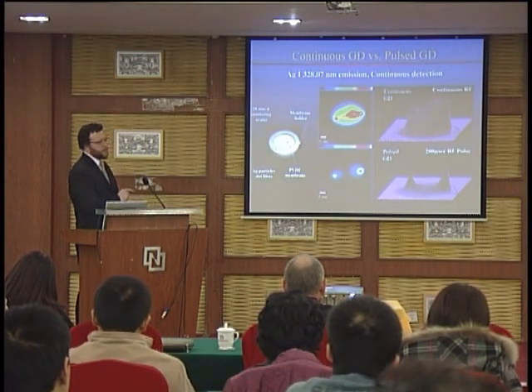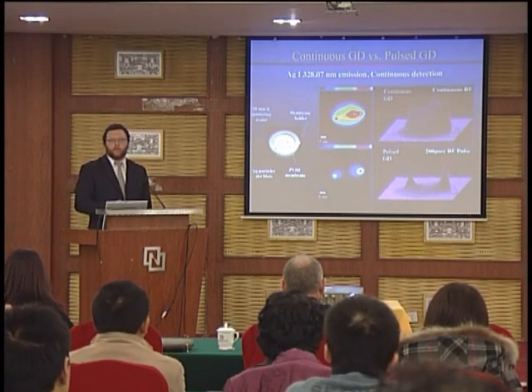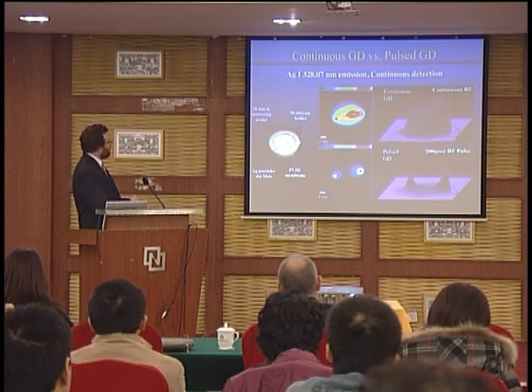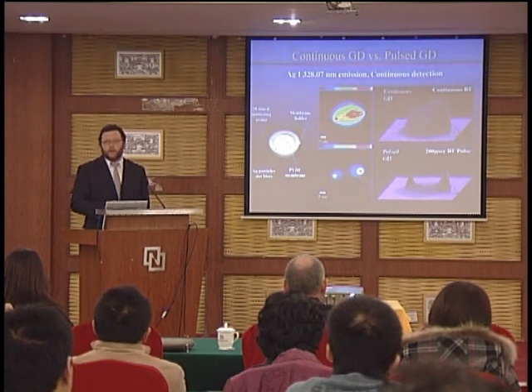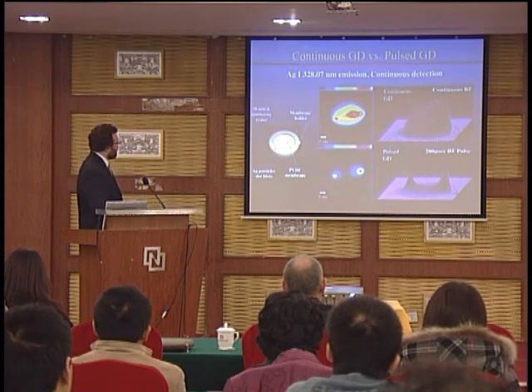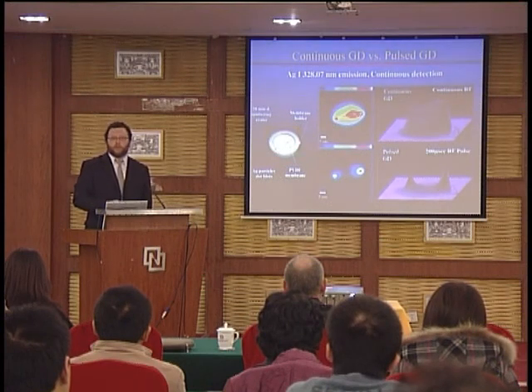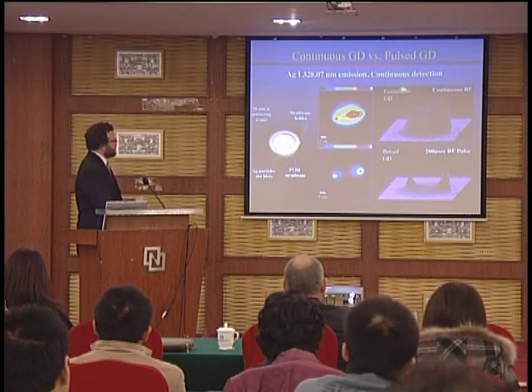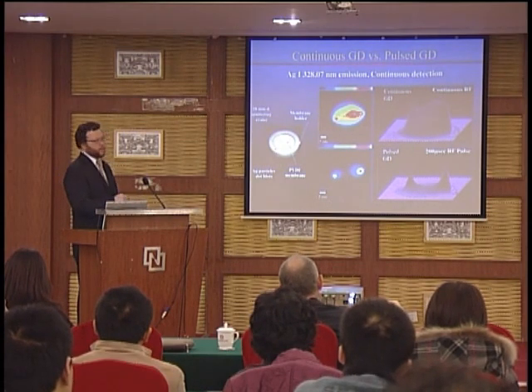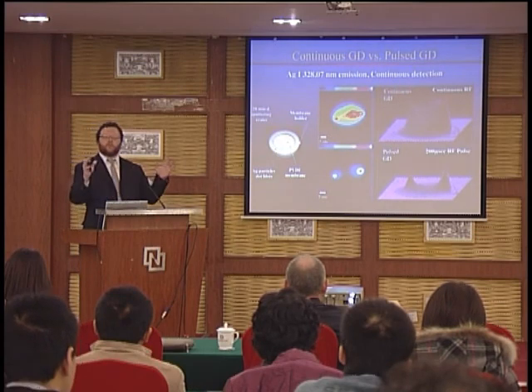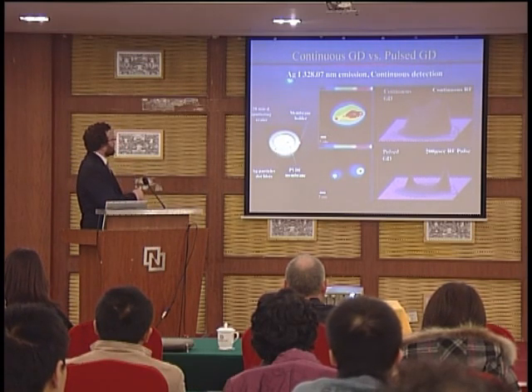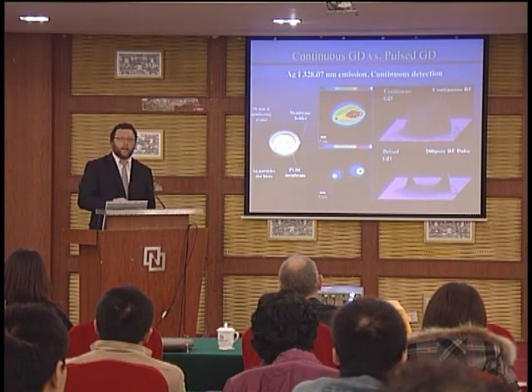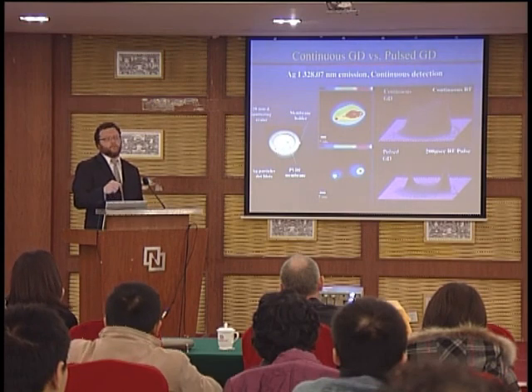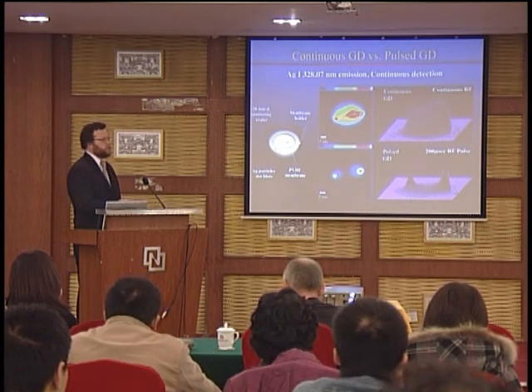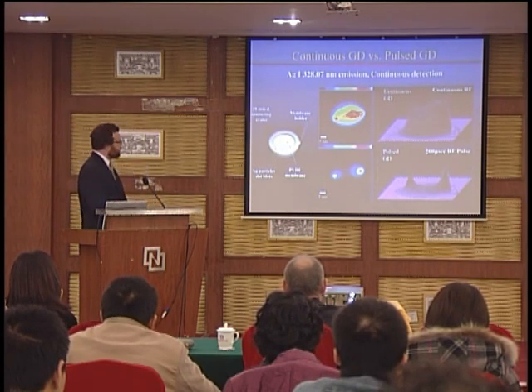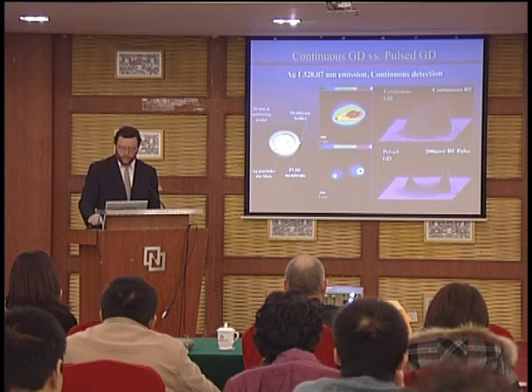This is a comparison of our continuous type of model with what we would achieve with a pulsed source. So what we did was we took a sputtering crater here. This happens to be a PVDF membrane, which will become important here in just a moment. It's an insulating material onto which we put 2 little dot spots of silver nanoparticles. And we imaged it using either continuous excitation or pulse excitation. And as we said before, under continuous excitation, all the diffusion simply smears out the emission profile here at the excitation of silver atom at 3280 angstroms. If you apply the pulsed waveform using a short lifetime, here on the order of 200 microseconds, we're using radio frequency because this is an insulating sample, you can see that we maintain that spatial resolution, which is the key to what we're trying to achieve here.